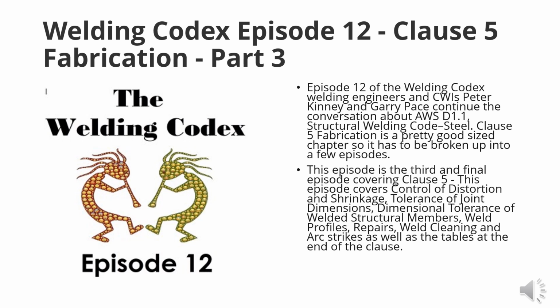Slag shall be removed from all completed welds, and the weld and the adjacent base metal shall be cleaned by brushing or other suitable means. Tightly adherent spatter remaining after the cleaning operations is acceptable, unless it is required to be removed for the purpose of NDE. Weld joints shall not be painted until after the welding has been completed and the weld has been accepted. So that's just common courtesy to the weld inspector. Hey, knock all the slag and crud off, because he's not going to look at it until you get it cleaned up enough to look at.